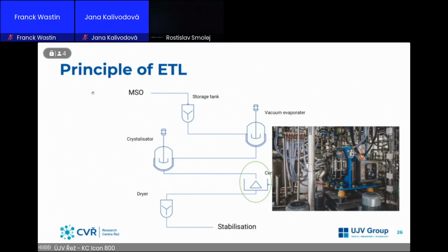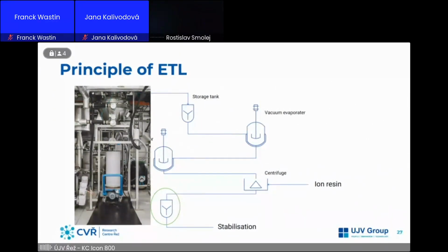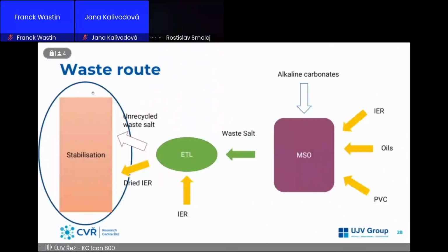And the next part is the centrifuge. It was one of the most expensive equipment we have, but when you do not oversaturate your solution, then you put it to the centrifuge and you will perfectly remove the solid part from the liquid part, which is great. And after that, you have the dryer. Also, you can see the drum for stabilization. The dryer is again a 2-shelled tank. It has the capacity of 90 liters, and the outer shell uses hot water to dry up the solid phase, but it also has cooling tubing inside. When you properly heat it up and dry it up, you need to cool it down a bit for the stabilization process. And now we are going to the end of my presentation about the stabilization process.